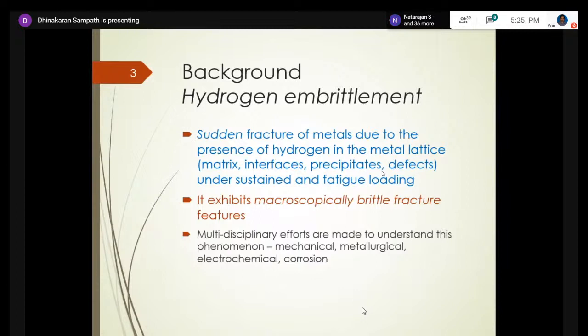So that is how it diffuses through the lattice. It stays in the matrix, that is the main metallic element in the alloy, or at interfaces in the microstructure, or precipitates, and also defects like point defects, line defects, and all forms of defects. Sudden fracture occurs under both sustained and fatigue loading. What I mean by sustained is constant load or monotonic loading, and fatigue load is cyclic loading.